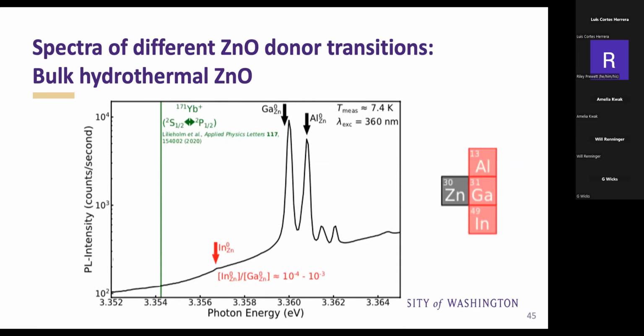Okay. This is what a spectrum looks like on a log plot where you can see aluminum. This is actually an excited aluminum state here, gallium, excited gallium state, and that indium transition you can just make out in this particular bulk sample right here. What has made our lives a little bit easier, here you actually see the ytterbium ion transition for ytterbium trapped ion quantum computers. We actually have a proposal to get these types of ions to talk to indium. But it's also helped us in terms of the optics that exist at this wavelength, given that the trapped ion community has really paved the way for near UV lasers.